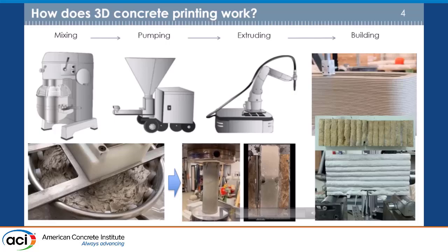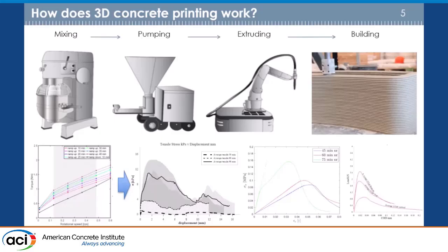And we have also seen in the last presentation what the challenge is to identify an interface fracture parameter, because the material is anisotropic, and if you want to simulate the structural behavior, you also need to know how the interface behaves and which are the properties that you have to assign to them. So basically, these are some of the results that we obtained in our lab with the different methodologies that I showed you before about the material thixotropy, early age tensile and compressive strength, and the anisotropic response in the different directions.